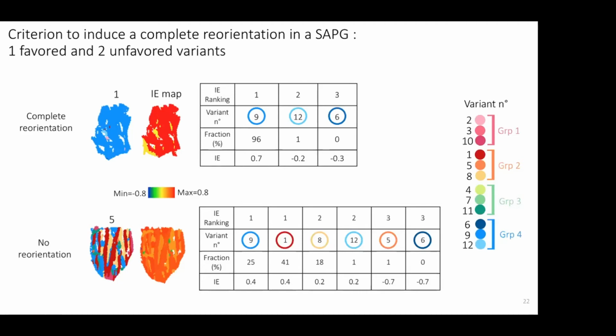And we can go further. We can say that to have a complete reorientation in a parent beta grain, it seems we need to have one variant that has a positive value of the interaction energy and two variants that have a negative value of the interaction energy. And the one that is favored, that means having a positive value of the interaction energy, will grow at the expense of the ones that are unfavored.